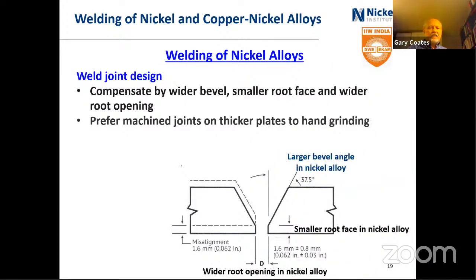So just like stainless steels, it's a matter of opening up the bevel, making sure that there's a wider root opening in the base if you're just welding from one side, and a smaller root face. And that's true for the high alloyed stainless steels and the nickel alloys.